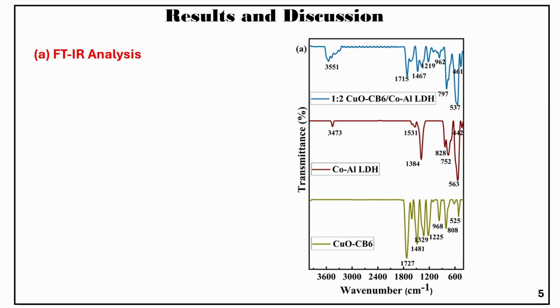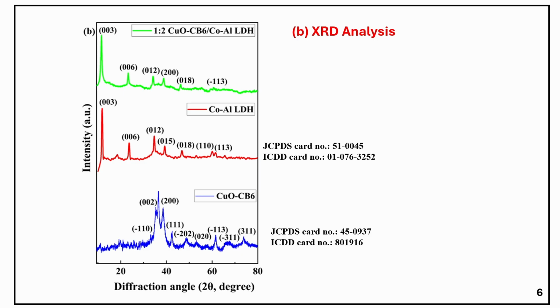Next, coming to results and discussion, FTIR spectral analysis was used to study the structural characteristics of the synthesized materials. The spectrum for CuO-CB6 showed peaks corresponding to the CB6 capping agent and a metal-oxygen bond, confirming the formation of CB6 stabilized CuO nanoparticles. Cobalt aluminum LDH exhibited characteristic bands related to OH groups and interlayer water molecules as well as carbonate ions. The FTIR spectrum of the 1:2 nanocomposite showed shifted vibrational bands compared to the pristine components, which confirms its successful formation.